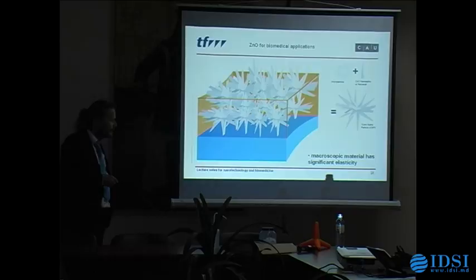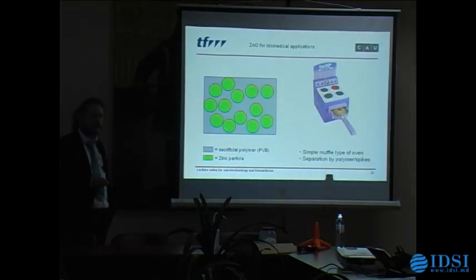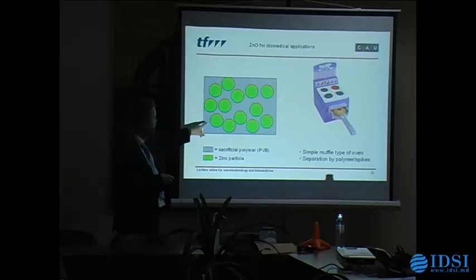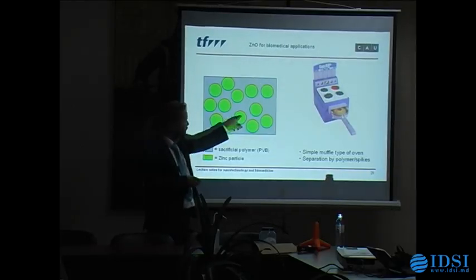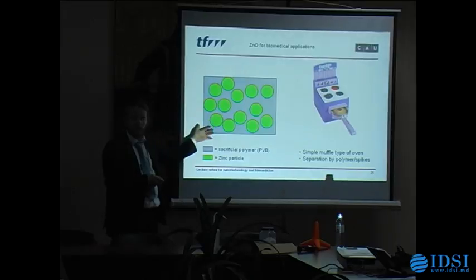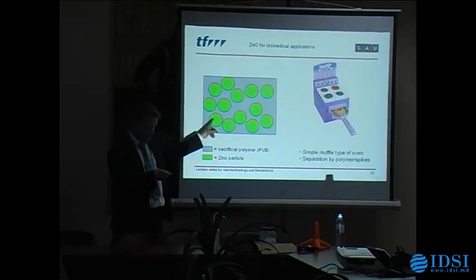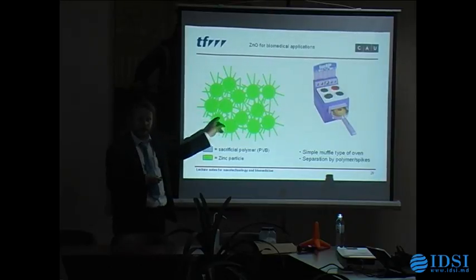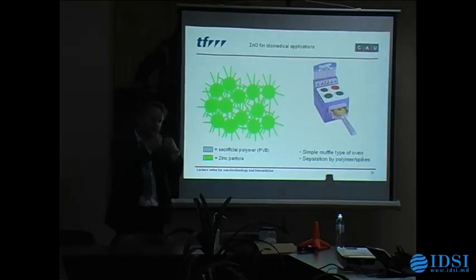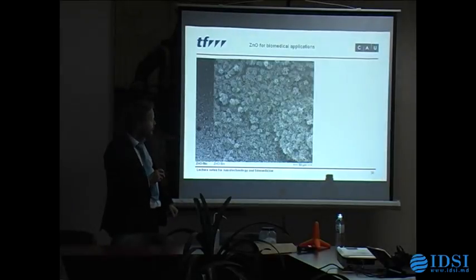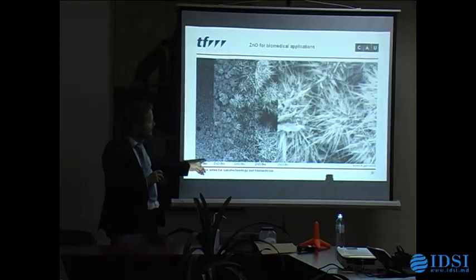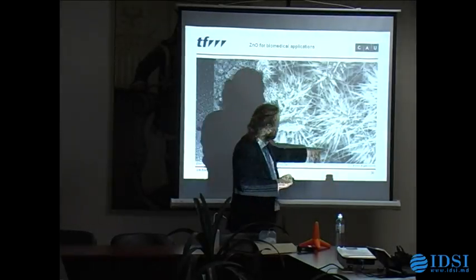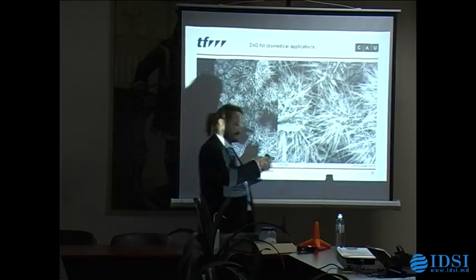But we wanted to do it in reality, so we built a very simple process to oxidize our zinc in a very simple oven. We took these zinc particles and had a sacrificial polymer which was just burned. And now you're converting this to zinc oxide. The spikes grow at the same time and penetrate. But it's not one mass, it's not like one zinc oxide block, but the whole thing is kind of nice and has a lot of free volume. And this was the result of these first experiments. You can see a lot of spiky material, and indeed only these spikes are interpenetrating.